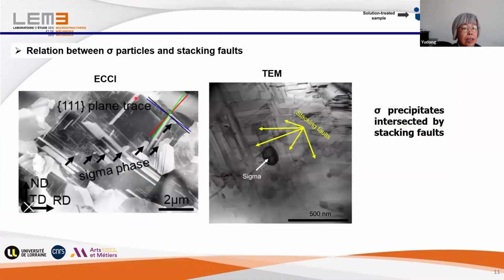And then we use SEM ECCI, electron channeling contrast imaging, to study the precipitation and also the defects. We see here are the sigma particles, and we have twins, annealing twins. And also we have these white lines, and these lines correspond to the stacking faults. And so we can see all these sigma particles are intersected by the stacking faults in different orientations.